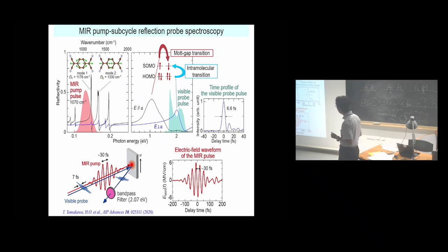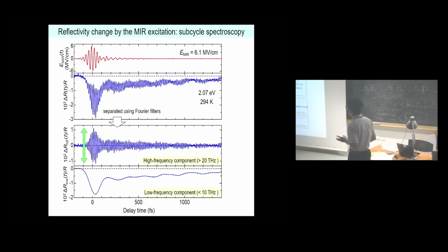This is the electric field waveform of the mid-infrared pulse, and this is its spectrum. The mid-infrared pulse excites this edge mode 1. The probe pulse covers this intermolecular transition band, and the time width is 7 femtoseconds. So we can perform the subcycle spectroscopy. The time evolution of the reflectivity change by the mid-infrared excitation is shown here. To analyze this signal, we separated the high frequency component and low frequency component using Fourier filters.